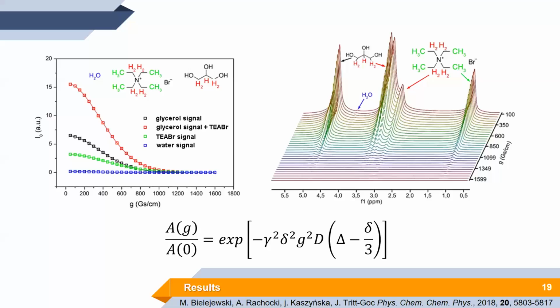So the first guess was that maybe something changed in the diffusion of the solvent molecules when it goes to gel. Because diffusion is directly related to the conductivity, because it describes how the charge carriers move. When the diffusion is faster, then the conductivity will also be higher. So with the use of pulse field gradient NMR methods, we measure the diffusion in the liquid electrolytes and in the gel phase.